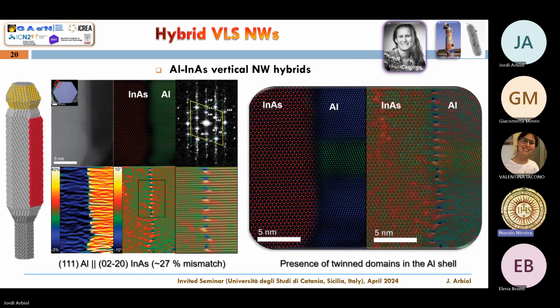Okay, so let's see what happened, because ideally for theoreticians that should work. And then let's go for experimentalists. We are the bad guys here, the electron microscopists. So okay, we have the indium antimonide or indium arsenide nanowire. In this case, this is a cross section. So we cut with a FIB, focused ion beam. You can cut a slice of this and then look at the slice. And this is indium arsenide, super nice. This is the atomic structure. You can see all the atoms here, super nice, super beautiful.